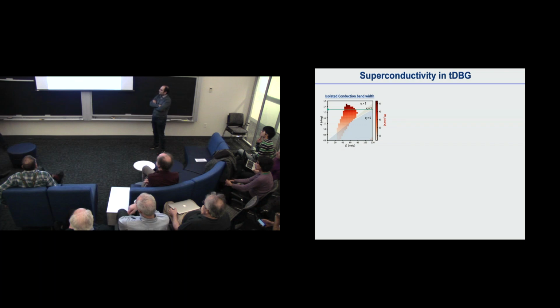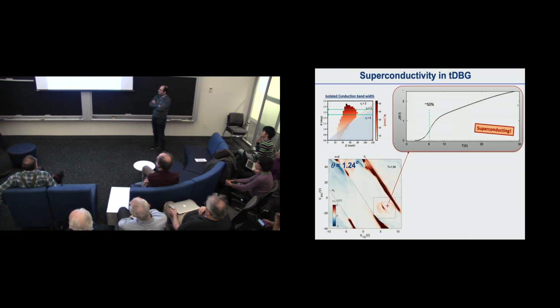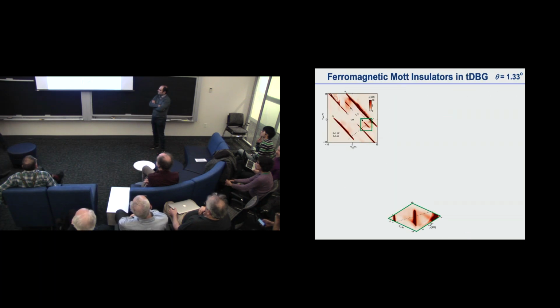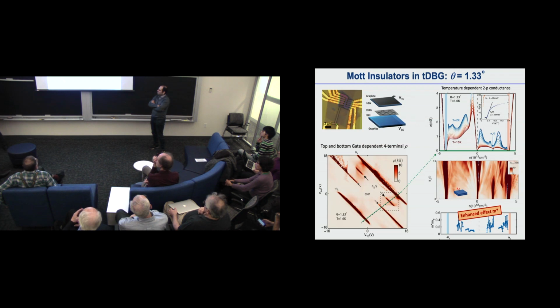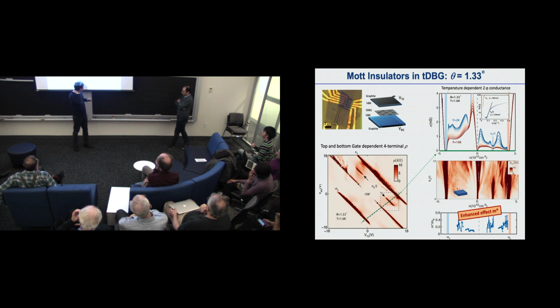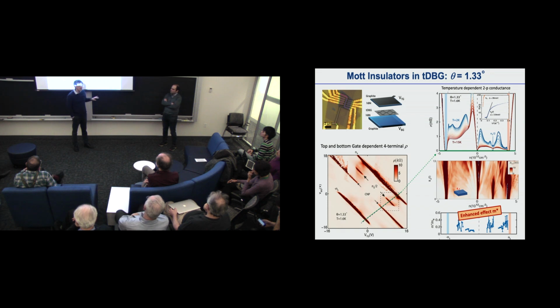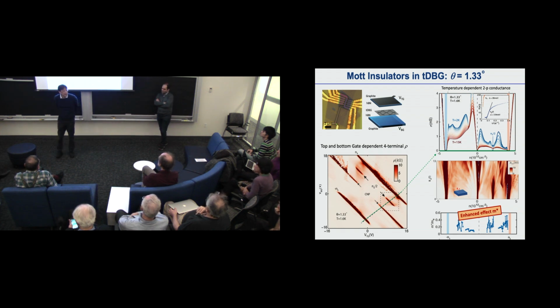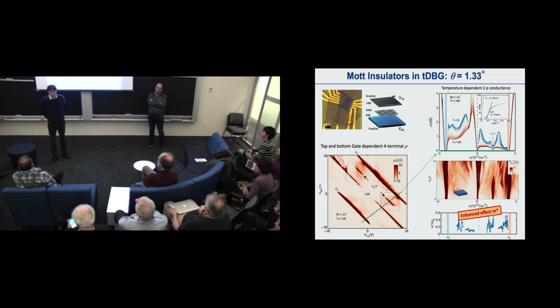No, I think it's the other way around. We have about 0.2 to 0.3-ish. So it's not heavy fermions, but the bare mass, the band mass here, is about 3 to 6% of the electron mass, but it's about 10 times enhanced. So compared with that, it's a fairly big enhancement—about 10 times more than just the bare electron mass from simple band structures.